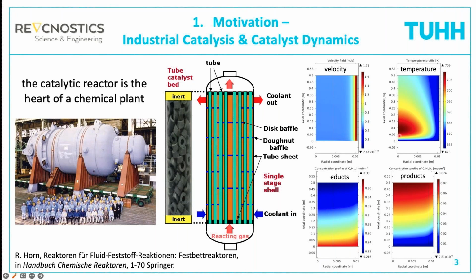Then we have temperature gradients. You see we have maybe for an exothermic reaction a hot spot here close to the entrance of the reactor. Then you have very pronounced temperature gradients in flow direction and in radial direction. And we have, of course, gradients in our chemical species. The educts are being consumed, the products are being produced. So we have very different conditions in the reactor. And now you might ask, why do I want to do at all spectroscopy in these reactors? I have a model. I can just optimize the reactor based on this model.